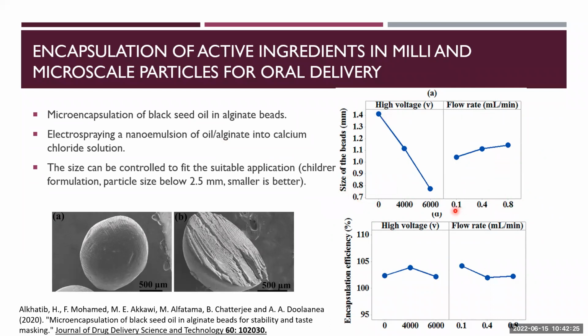The flow rate between 0.1 to 0.8 or up to 1 mil per minute has almost no effect on the size. But if you go higher, usually the size becomes bigger. But both flow rate and high voltage didn't affect the encapsulation efficiency. And this is quite good because we can see that the process didn't affect the encapsulation efficiency as far as we are using the same formulation.